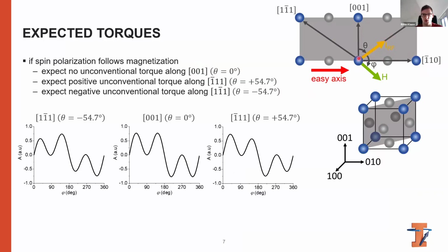But if we apply current along the 1 bar 1 1 direction, which is the positive 54.7 degrees, we expect positive unconventional torques because the spin polarization would have a component parallel to the current. And then for the opposite angle, we expect negative torques because the spin polarization would have a component anti-parallel to the current.